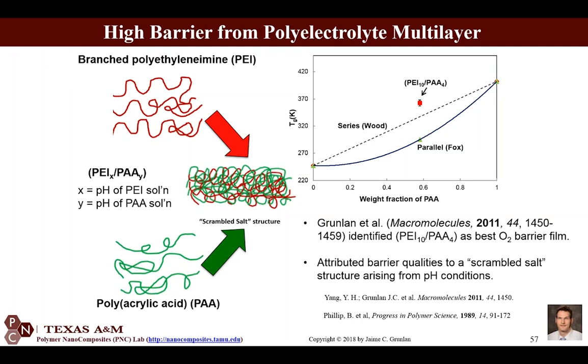So what we're seeing here now, I had mentioned putting these layers between the clay, and some people over the years had asked me if I only took a look at that polymer system, the polyethyleneimine with the polyacrylic acid, what would happen in this case if I tested its gas barrier? And I assumed it would be very bad because it's just a completely polymer thin film. What we did see, though, is when you combine polyethyleneimine and polyacrylic acid, you've got a polyacid and a polybase, and they really love each other more than they love themselves.